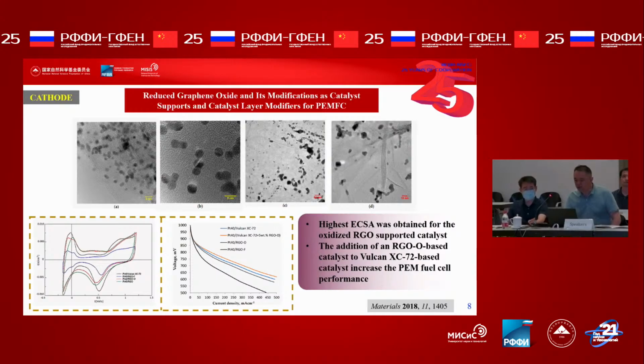The structure and the electrochemical properties of the obtained catalysts were investigated in an electrochemical three-electrode cell and in PEMFC, that is called proton exchange membrane fuel cells. Among the RGO-based catalysts, the highest electrochemically active surface areas, the ECSA, were obtained for the oxidized RGO-supported catalyst. And we can see that the addition of the RGO-O-based catalyst to the Vulcan XC-72 based catalyst shows an obvious increase in PEM fuel cell performance.